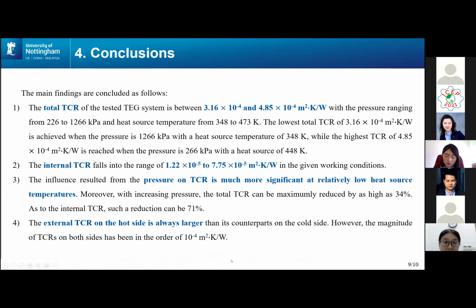So, from our experiment, some important conclusions can be made. The main conclusions are listed here. The value of different TCRs can be obtained. It should be noted that the pressure's impact on TCR is much more significant at relatively low heat source temperatures. The external TCR on the hot side is always larger than its counterpart on the cold side. From our experiment, we can see that the load pressure plays a vital role in influencing the TCRs and the performance of TEG system.